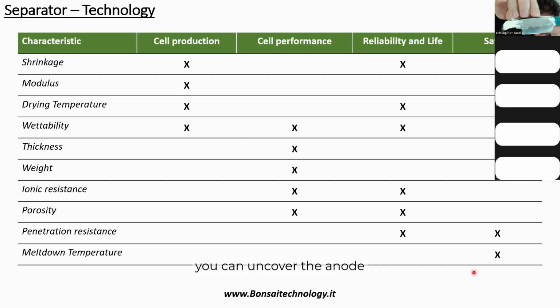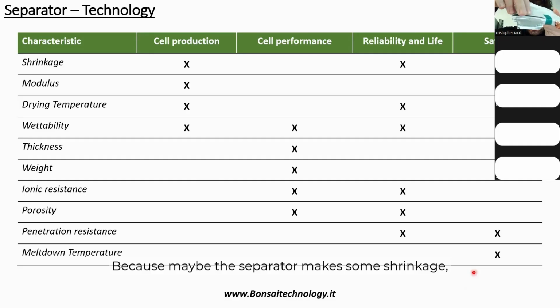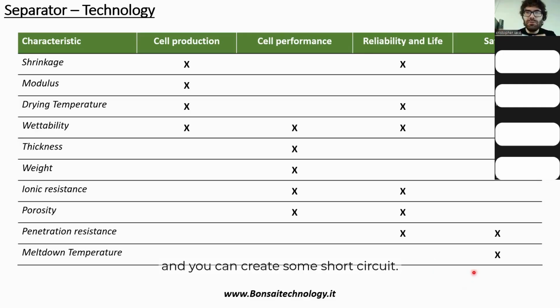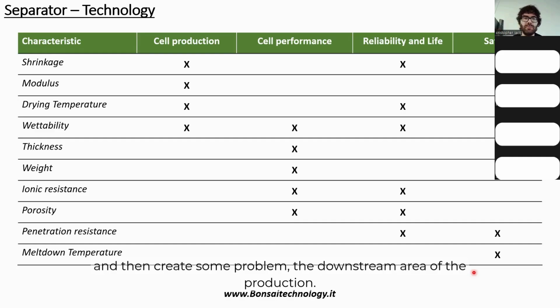you can uncover the anode with the cathode, because maybe the separator shrinks, and then you expose the anode and the cathode, and you can create some short circuit, and this is not good for the batteries. But this can affect even the cell production, because the shrinkage effect could occur during the drying process, or during other processes where the cell goes through a very high temperature. So in this case, the separator can suffer shrinkage and then create some problems in the downstream area of the production.